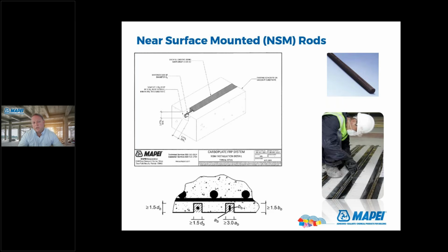Because you would be concerned with the abrasion if you just use the fabric on the top. Over time, the tires are going to tear through the epoxy and eventually the fabric. So by embedding it into the concrete member, it's going to help prevent the FRP from getting damaged.